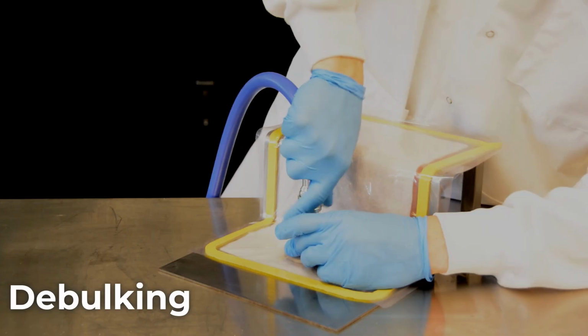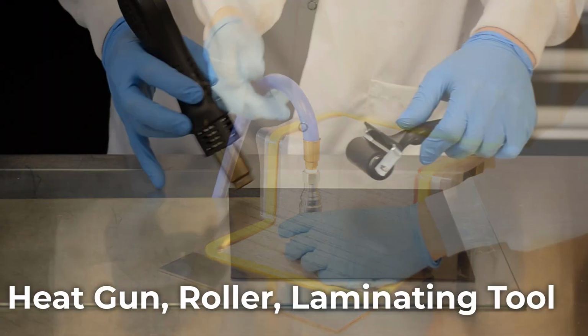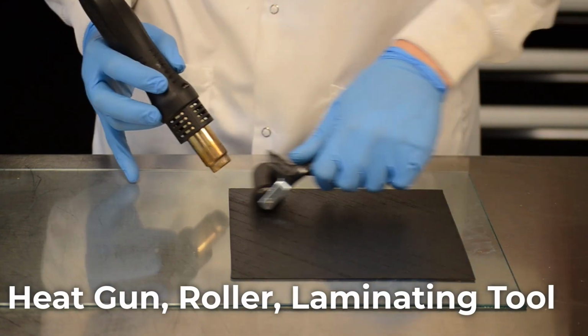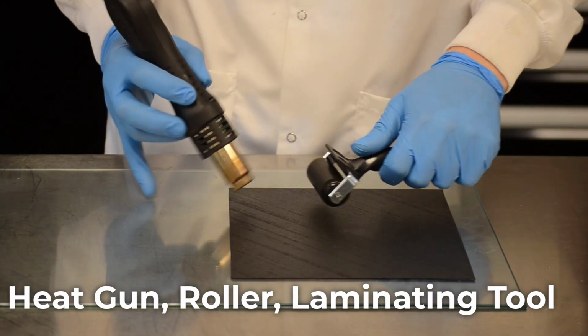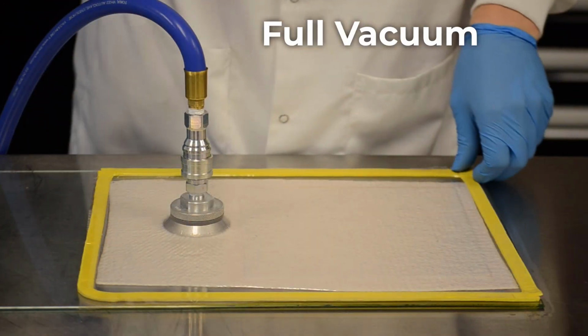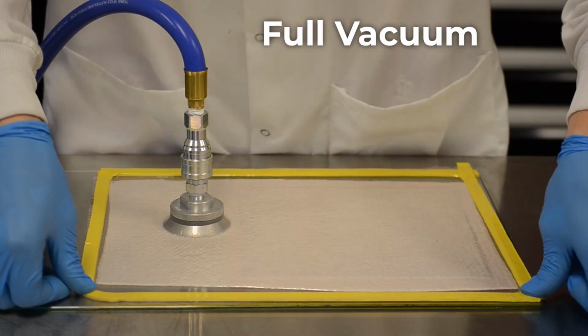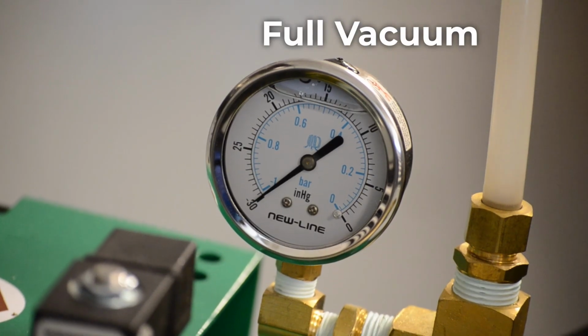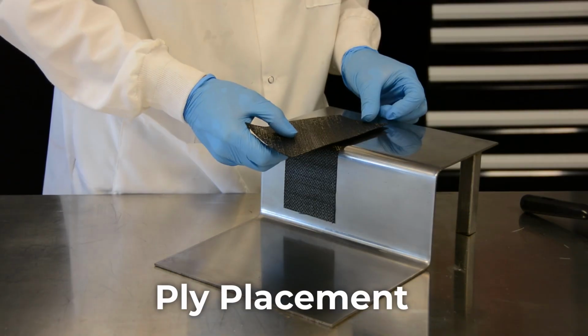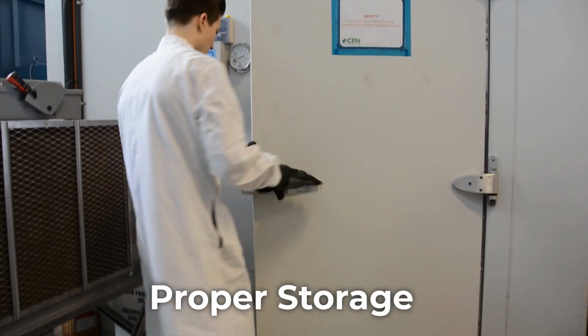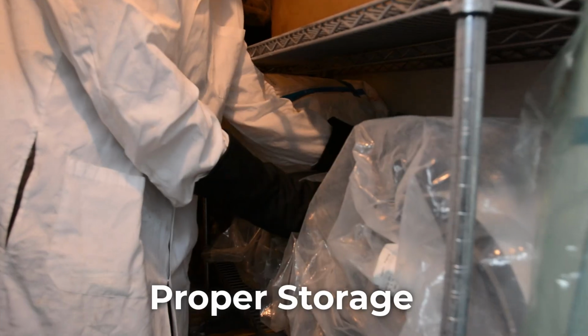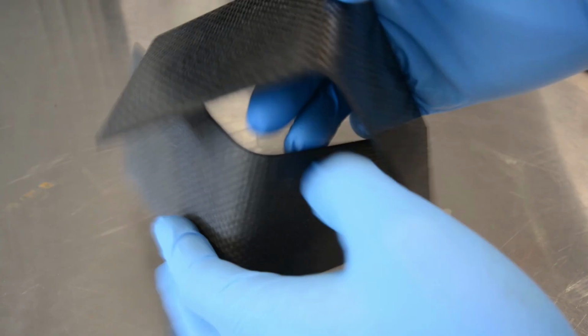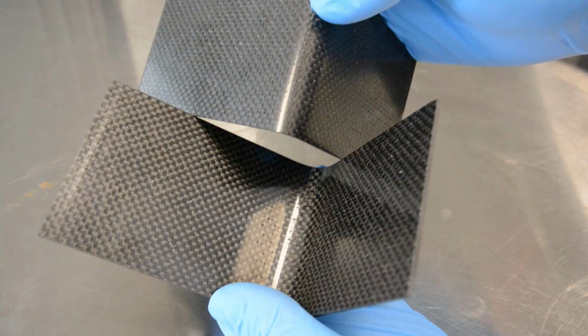the plies are closely following the tool geometry, using a heat gun to increase drapability and tack to facilitate ply placement, ensuring full vacuum is pulled on the part and that there are no leaks in the vacuum bag or tool, placing plies accurately, storing prepreg properly to prevent excessive out time or moisture absorption. If good layup practices are followed, the occurrence of many defects can be reduced and part quality can be improved.